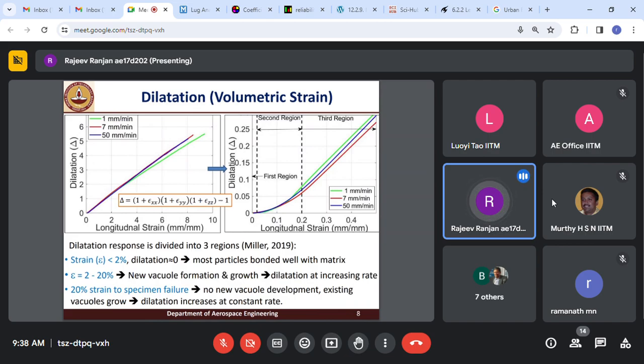Since in composite solid propellant, the matrix is a polymer material, which is nearly incompressible, and the solid particles are comparatively rigid, they don't undergo any volume change. So whatever dilatation we observed, we can say that it is coming from the vacuole formation in the material. So based on that, we divided the dilatation response into three regions.